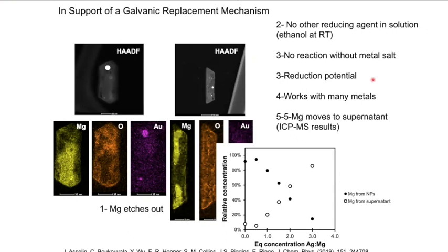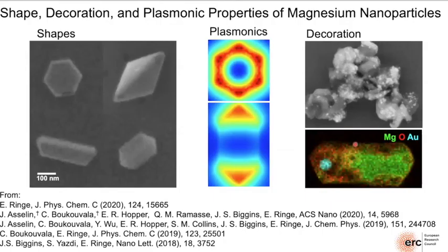There's, again, a huge thermodynamic driving force in the reduction potential. It works with essentially, well, not all metals, but most metals. And we can then also track the magnesium movement to the supernatant, so we can actually look at the magnesium ions. And indeed, as we change the stoichiometry of the reaction, we're basically leaking out magnesium ion into the supernatant. So we're quite confident this is a galvanic replacement mechanism. We published this just last year. I think that's it for today.